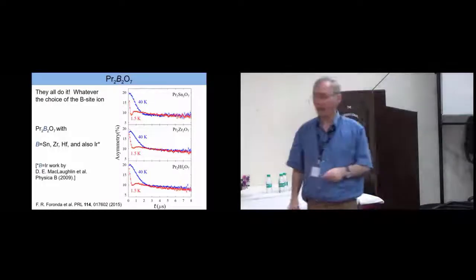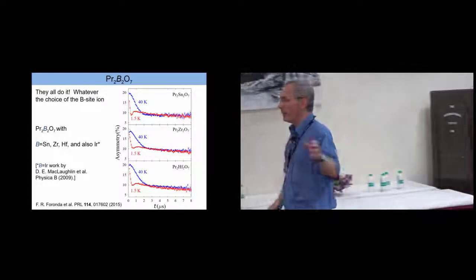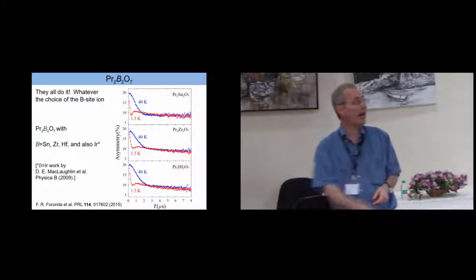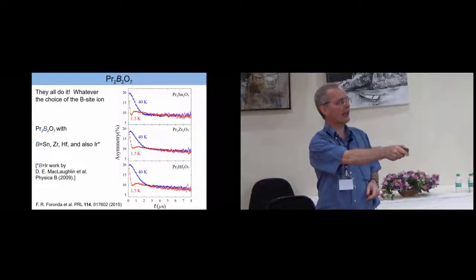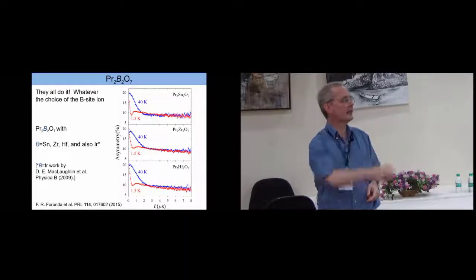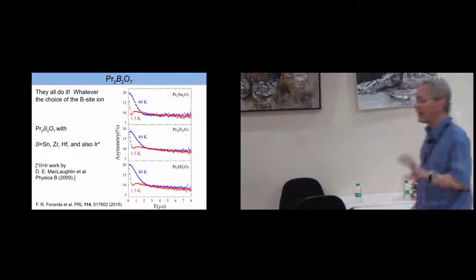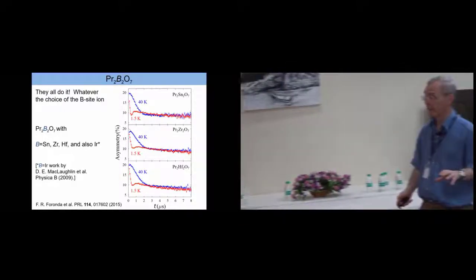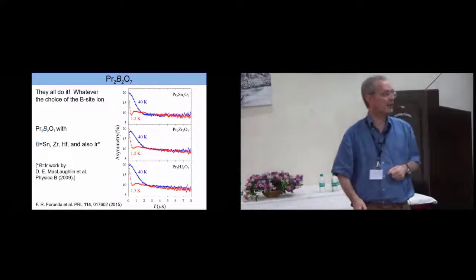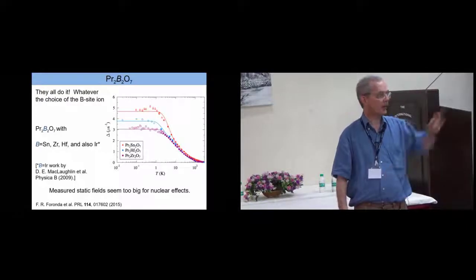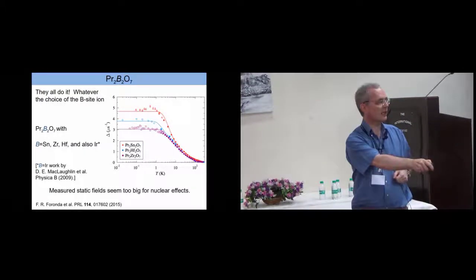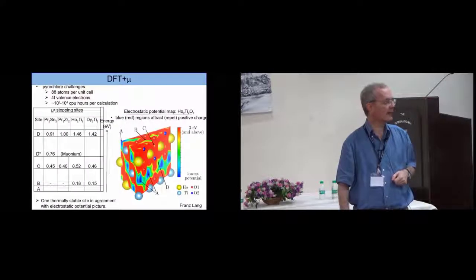And what's also rather intriguing, we thought maybe it's something special about praseodymium stannate, but we did praseodymium stannate, zirconate, hafnate. Someone else had done praseodymium iridate, and they all show the same thing. So there's something odd about this material. So they all show this strange temperature dependence. And the measured static field seemed too big for nuclear effects.